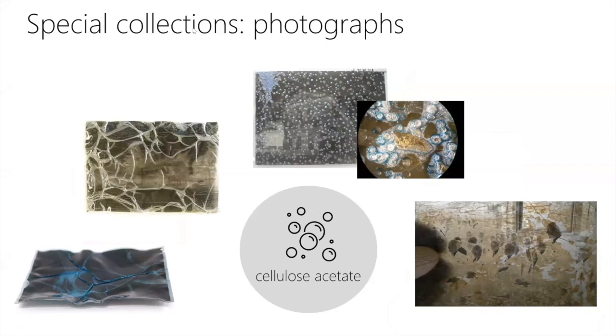Cellulose nitrate were substituted by cellulose acetates, also known as safety films, introduced in the 20s. However, cellulose acetate rapidly proved to be as chemically unstable as cellulose nitrate, the film showing a typical degradation pathway known as vinegar syndrome. Some of the deteriorations include vinegar odor, curling, curving, channeling, bubbles, blue, pink, or other color stains, among others.